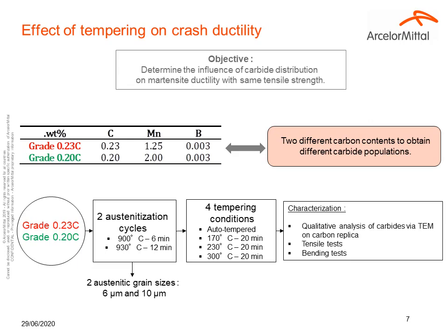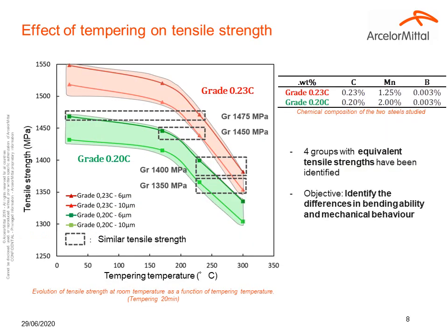Then the characterization, thanks to qualitative analysis of carbide via TEM on carbon replica, but also tensile test and bending test. We are first going to start with the evolution of tensile strength. On this graph, the evolution of the tensile strength as a function of the different tempering temperatures for our two steels and two different heat treatments. We can see first that the grade 0.23 has a higher tensile strength than the 0.20 for the same tempering treatment.